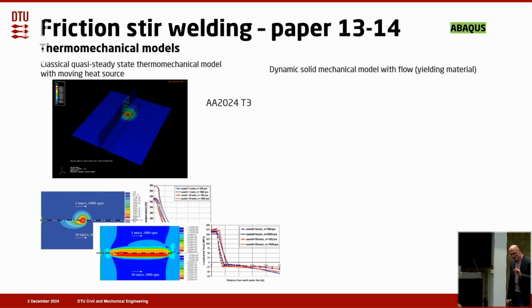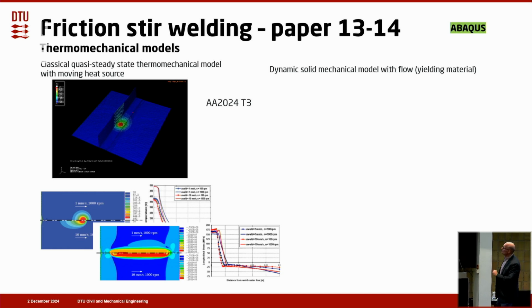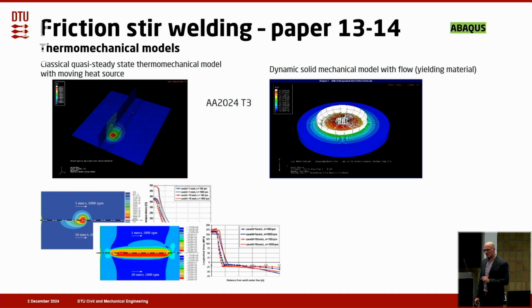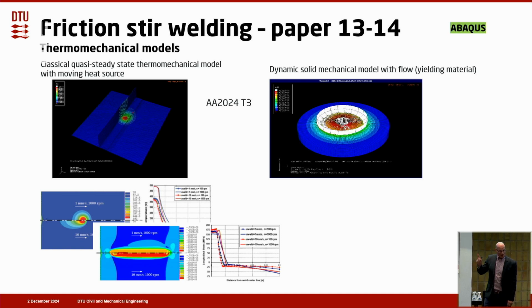Then we did a much more advanced model, a dynamic solid mechanical model with flow. This is what you see here, just at the very beginning of the friction stir welding. The very interesting thing about this model is that the interface condition between the material, between the tool and the matrix, is not prescribed. It's part of the solution itself, and that made it very special, this model.